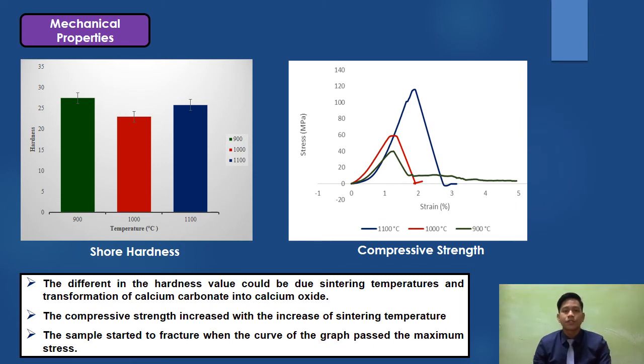Based on the results of Shore hardness, the difference in the hardness value could be due to sintering temperatures and transformation of calcium carbonate into calcium oxide. According to the literature, hardness increases as eggshell percentage in the matrix material increases. Sintering temperature and compaction pressure affect the material's hardness. For the compressive test results, the compressive strength increased with the increase of sintering temperature due to the formation of a dense structure. The sample started to fracture when the curve of the graph passed the maximum stress.